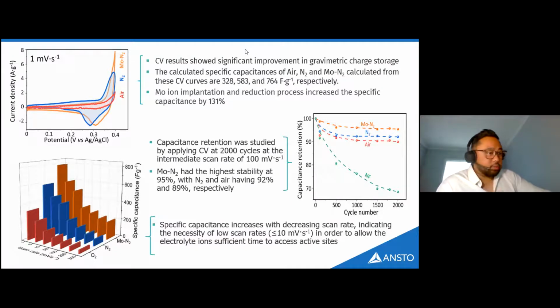And lastly, the figure on the right, we assessed the capacitance retention using cyclic voltammetry for 2000 cycles. And what we could find was that the ion implanted sample had the highest stability at 95%. Overall, the molybdenum implanted nitrogen annealed sample exhibited the best performance in terms of gravimetric capacitance, discharge period, and capacitance retention. So hopefully these couple of brief samples show how ion beams can be used as an additional tool to modify the functional surface properties of advanced materials.